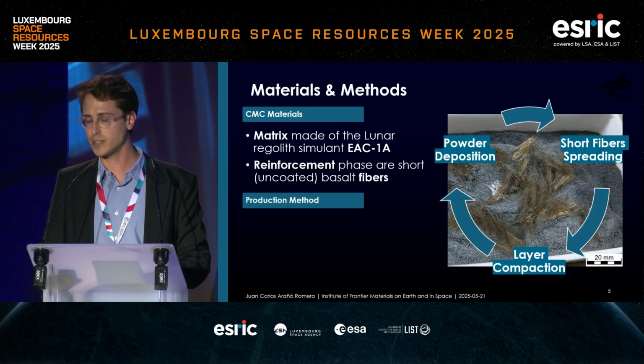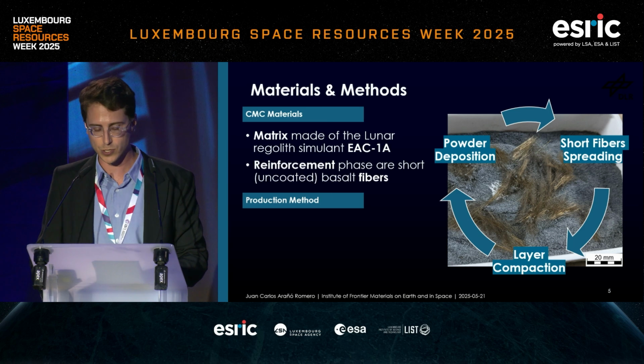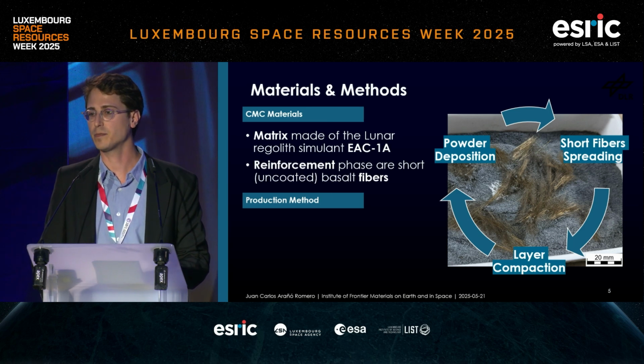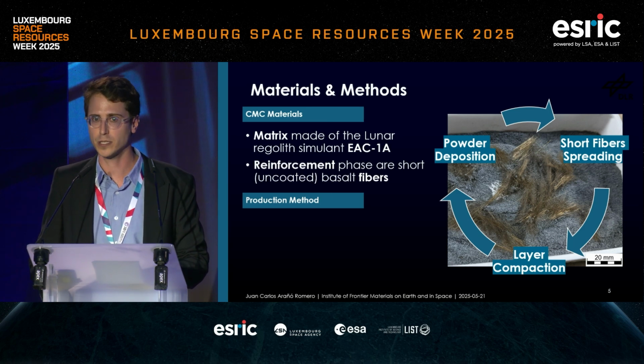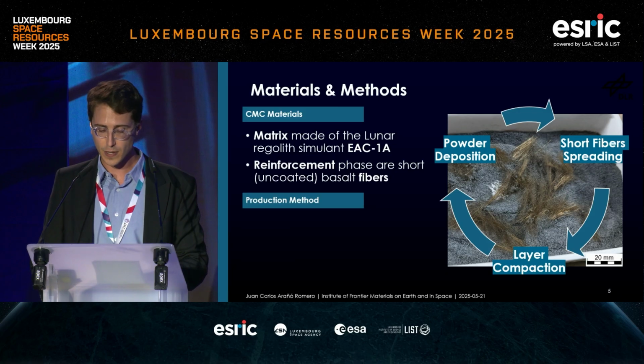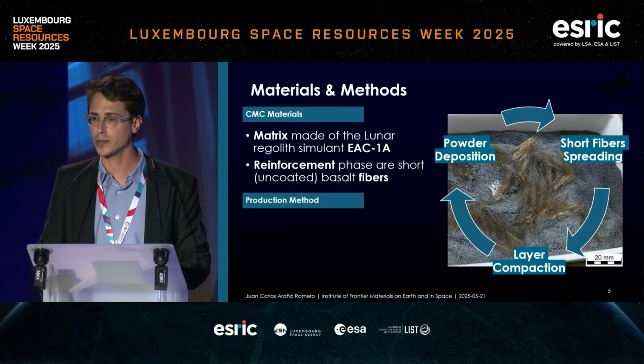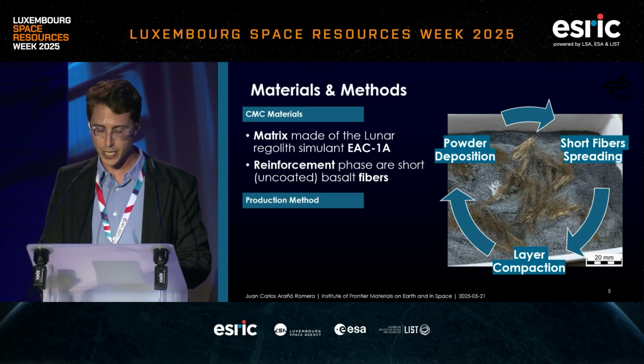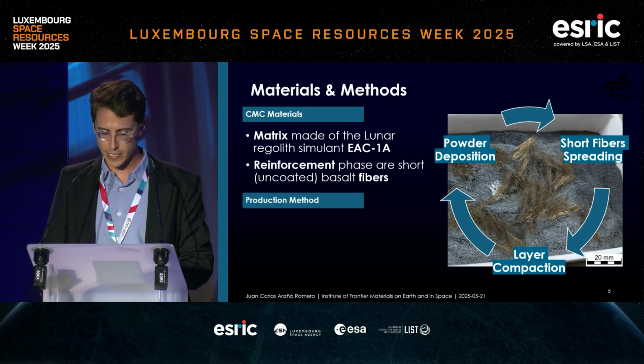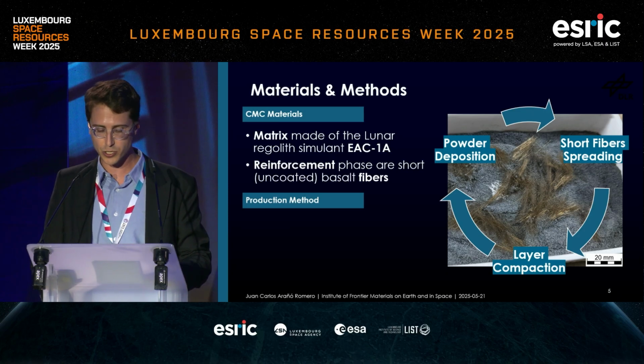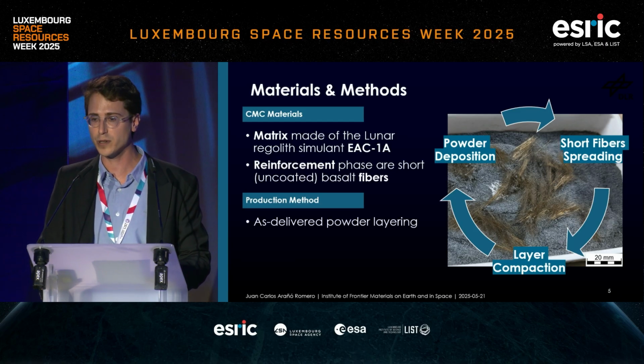The diagram basically summarizes the process, in which we layer the powder, which was previously dried. Then we spread the fibers, as I mentioned, randomly over the powder layer, and we compact each of the layers. Then we sinter the whole structure under different conditions, and with this setup, we produce multiple samples. So let's take a look at how they perform.